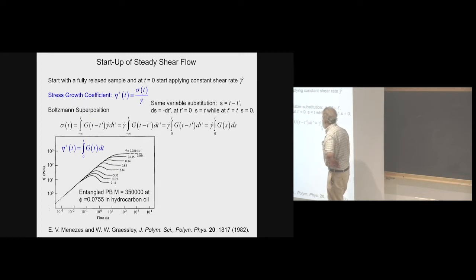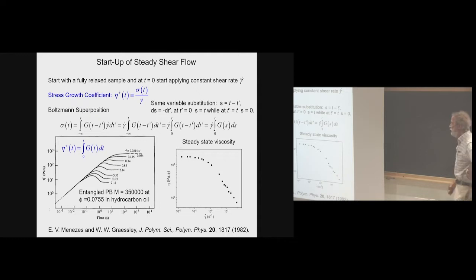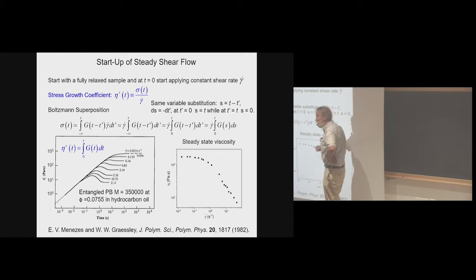And so these are very nice data, and we can use that flat part to say that's the real steady state viscosity at each of those shear rates, and then I can plot that steady state viscosity as a function of shear rate. So a word of warning: it's important to do this experiment if I want to believe these